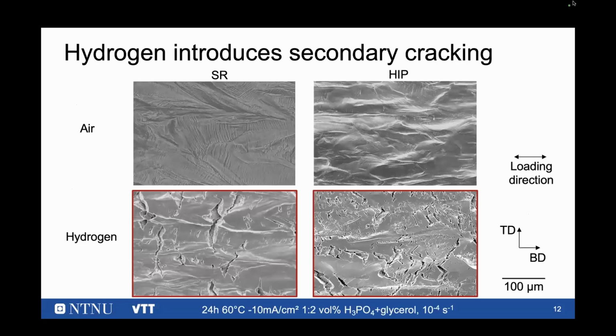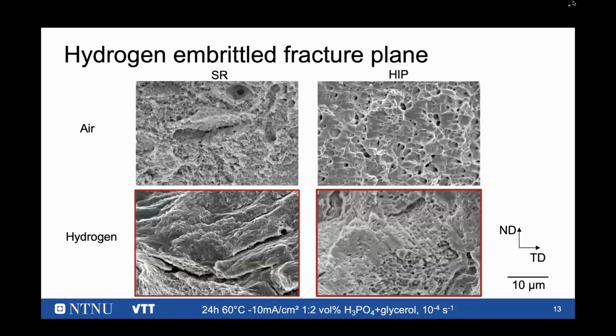First, in the fractography, what do we see? In both cases in air, there are a lot of slip lines, no cracks present. On the other hand, in the hydrogen case, we see many secondary cracks present. The crack density is even higher in the HIP condition. Similar, expected results are on the plane.